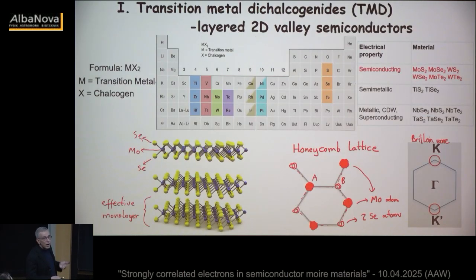All right, so now I told you that the material of interest for us is transition metal dichalcogenide. I told you about 5,000 layered materials. I don't know the number, but there are probably tens of transition metal dichalcogenides in this system. Some of them are superconducting, some of them are charge density waves. We'll be interested in this subclass, which is semiconductor. If you look at it from afar, they have a honeycomb lattice structure where the inversion symmetry is broken because A sites consist of a metal atom, say molybdenum, and B sites consist of two chalcogen atoms. Here in the first part, this will be selenide, in the latter part, it will be telluride.